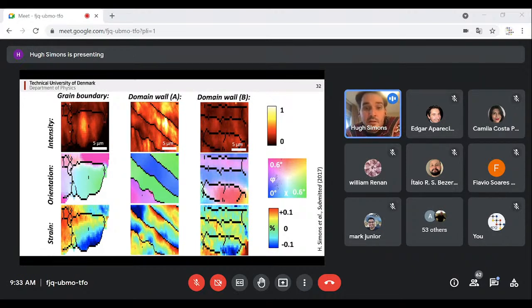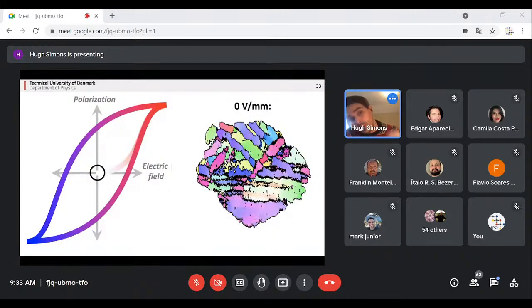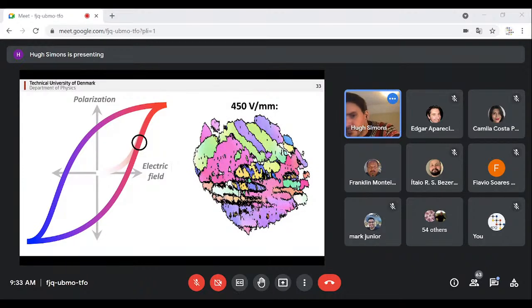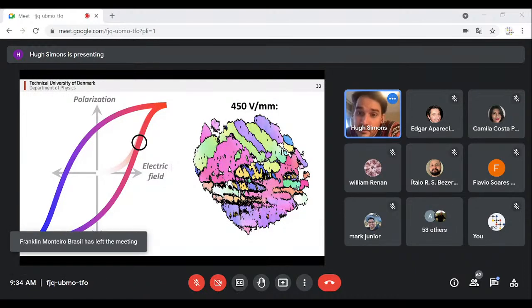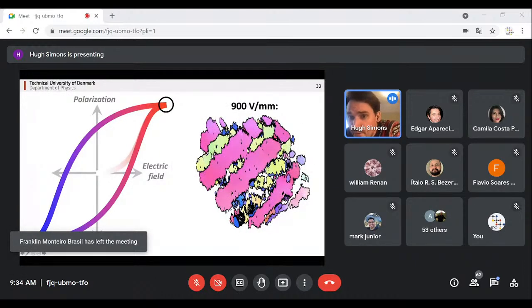And this has a really dramatic impact on the way that these domain walls self-organize during electric fields, for example. In ferroelectrics, when you apply an electric field, you have this very characteristic polarization hysteresis. This occurs as the domains reorient and essentially change their volume fraction as the electric field is applied. And the beautiful thing is that because we have lots of space around the sample when we do these experiments, we can afford to put electric fields on and track how the domains reorient. And this is exactly what we did. As we applied an electric field, you start to see the pink domains get much larger because they correspond to domains which are oriented parallel to the electric field, until they form these nice big stripe patterns.